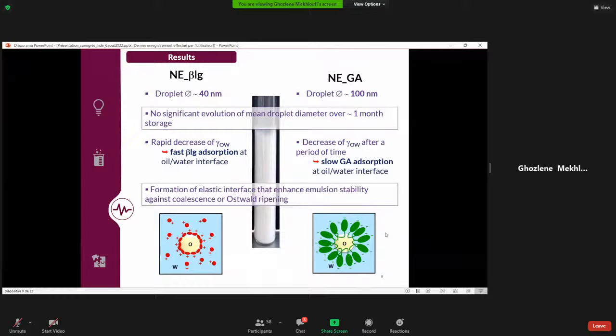As you see here, we obtain nanodroplets nearly twice smaller for nanoemulsion stabilized by the protein than those stabilized by the polysaccharide, which is normal because the protein is a smaller molecule than the polysaccharide. However, these nanodroplets are stable over 1 month of storage for both systems, and we saw no creaming phenomenon for this 1 month storage.